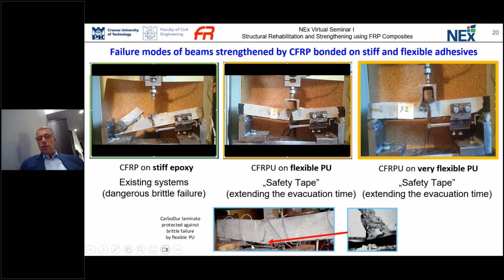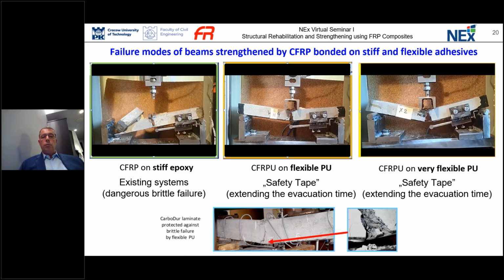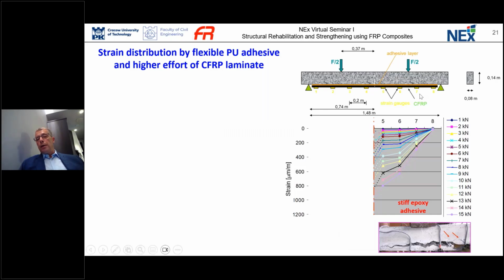Also, as you can see here, there is high stress concentration acting on the composite material, where typically, if it is stiff material, such a structure doesn't work, but with flexible material, it is able to work. If we compare the effort of this composite material when we have stiff epoxy resin, we can compare it here according to the load. But finally, we can expect very sudden failure, especially in the weakest part, that is reinforced concrete, the place of location of reinforcement in the concrete.